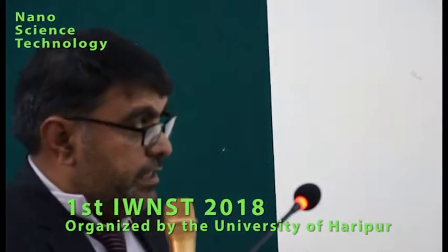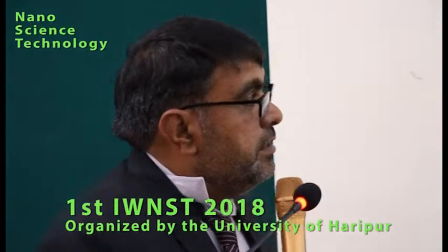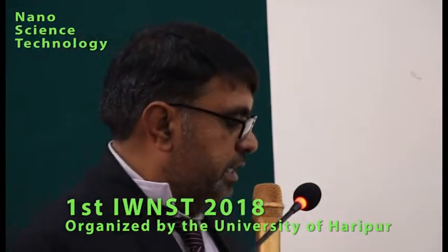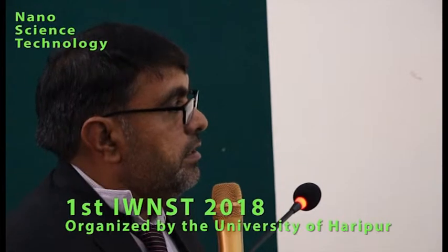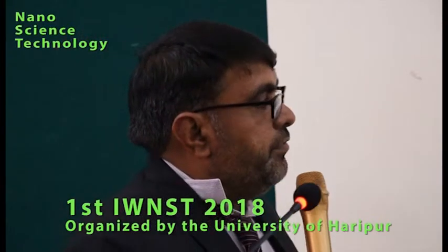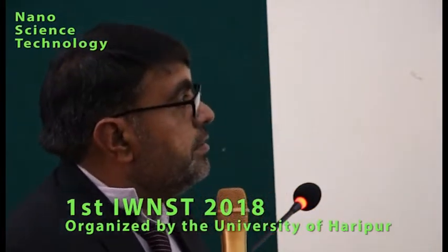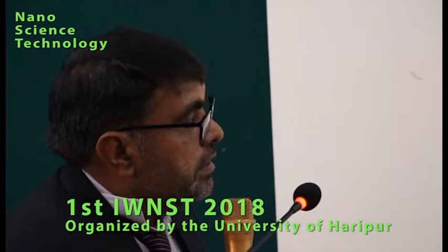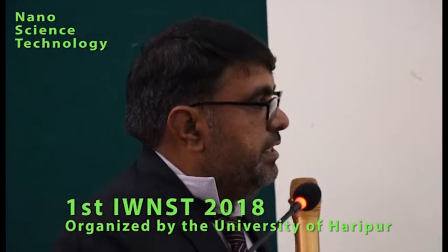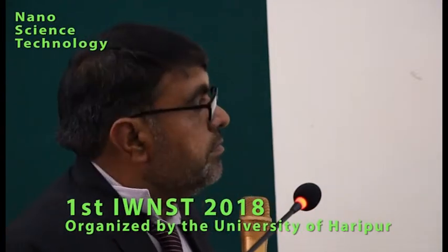In the second stage, we integrate the nanoparticle on the surface of the zeolite. Zeolite is basically used as a support, and the nanoparticle is used for the catalytic activity. We see the surface morphology is greatly improved by the integration of nanoparticles on the surface of zeolite. Here are some results and elemental distribution.